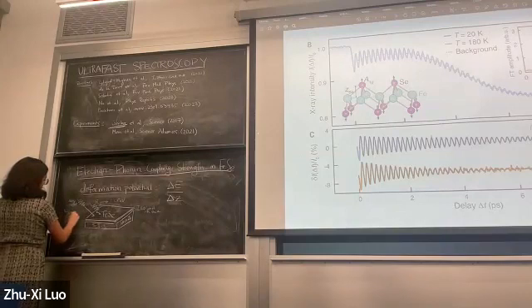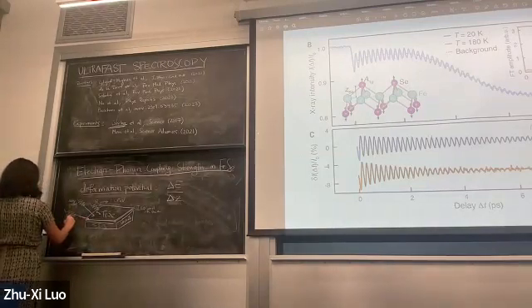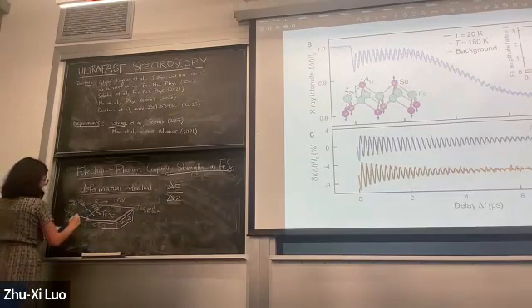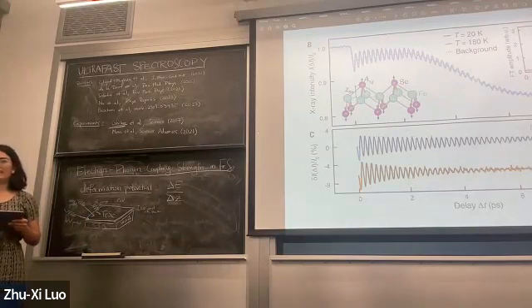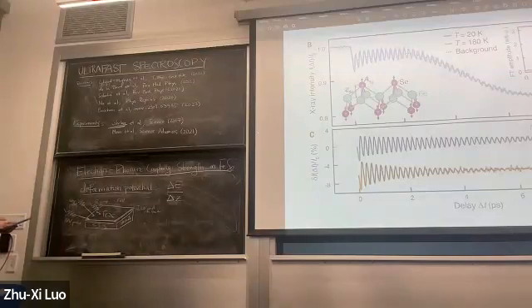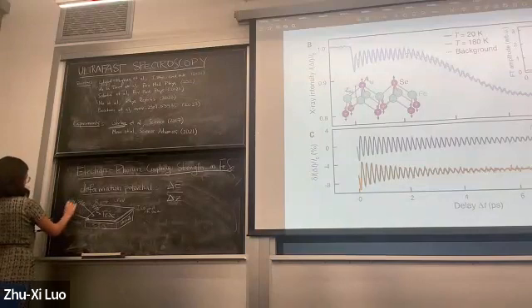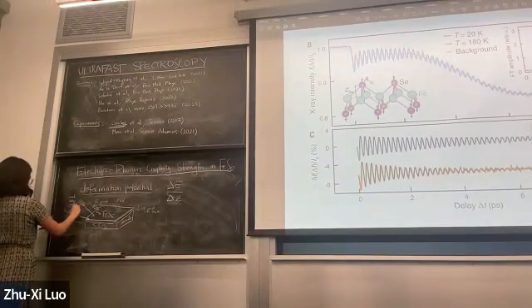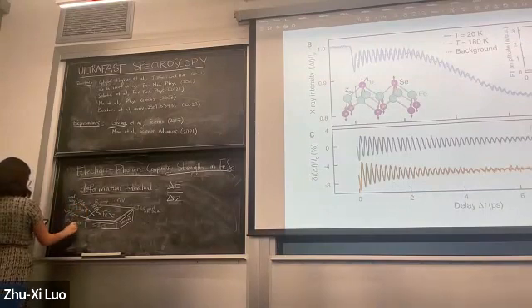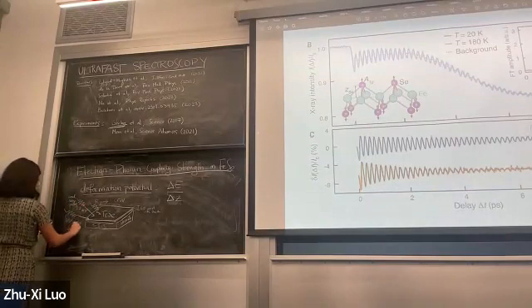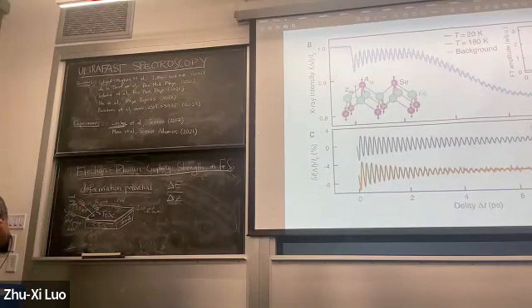And there's also going to be a UV probe, which we'll use to do the ARPES experiment and get information about the band structure and the dynamics of the band structure. And this X-ray probe is hard X-rays at 8.7 kiloelectron volts. And the UV probe is 6 eV light, which is produced using the prototypical method in these pump probe experiments, which is frequency doubling using some birefringent crystal.